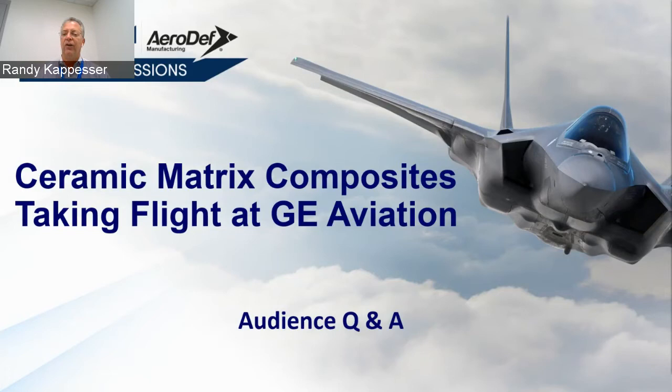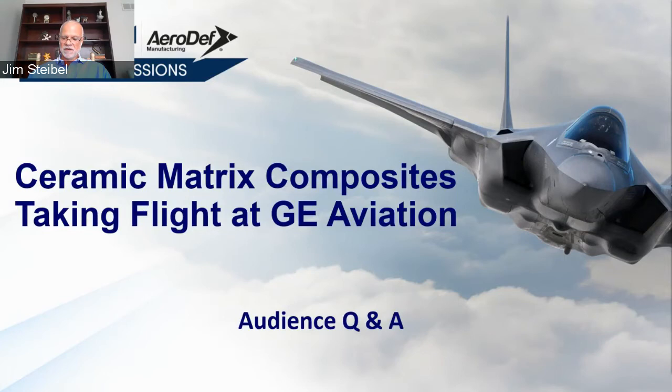That's a lot there. So there's a couple aspects. There is a regime of pressure and temperature and gas chemistry that leads to degradation of the oxide that's formed on the CMC if it's uncoated and bare. So therefore, we use the barrier coating to deal with that. Now, for the barrier coating itself, there are common methods again, like plasma spraying, used for thermal barrier coatings on metals that we employ. Again, we have to tailor it for our materials and whatnot. But those traditional processes do give us bonding that's suitable to give us the very long lives for these coated parts.